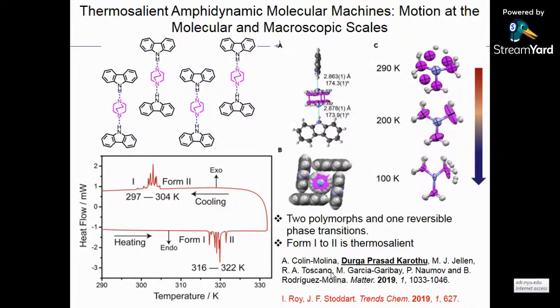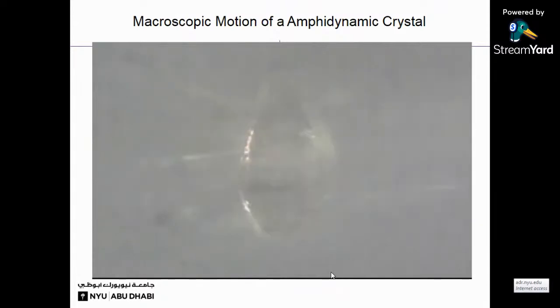The most interesting thing is at low temperature, the rotation is slower. At high temperature, the rotation is faster. But apart from this rotational dynamics, these crystals also have some kind of phase transition. As you can see in this DSC thermogram, when you heat just above the room temperature, these crystals show thermosalient behavior similar to that sawtooth behavior. You cool it to below room temperature, they come back to their reversible shape. So you can do several cycles. But the most interesting thing is what happens. The rotation of this DABCO molecule significantly decreases during the phase transition, either heating or cooling. And so when you heat these crystals, they jump instantaneously.